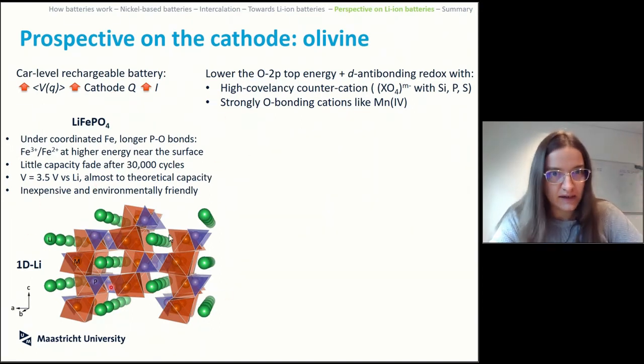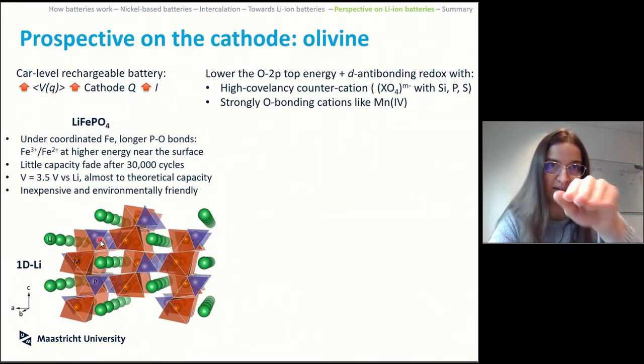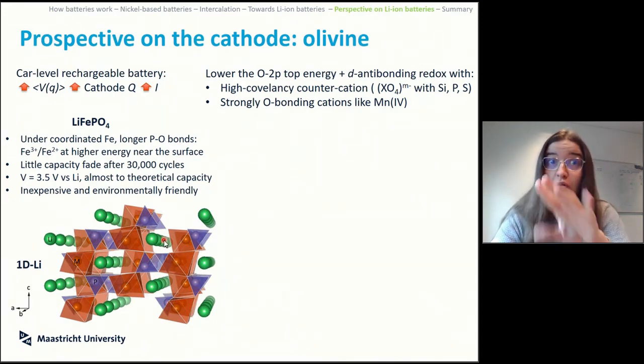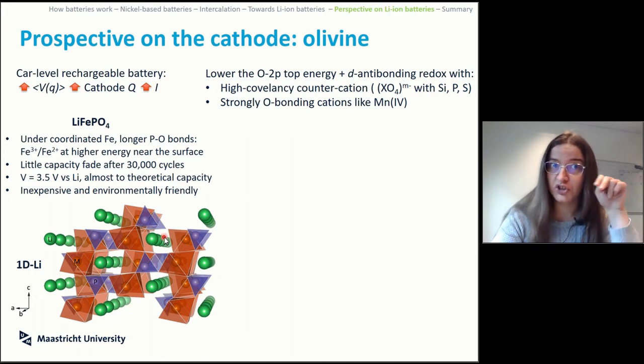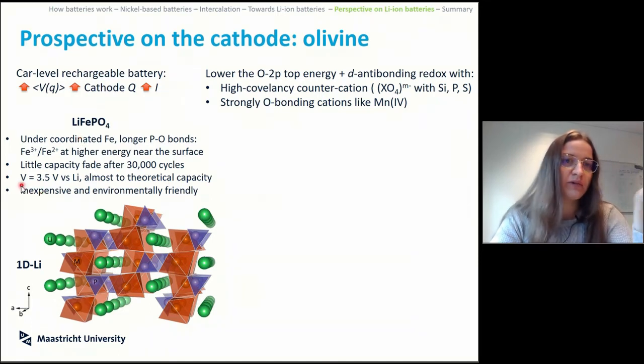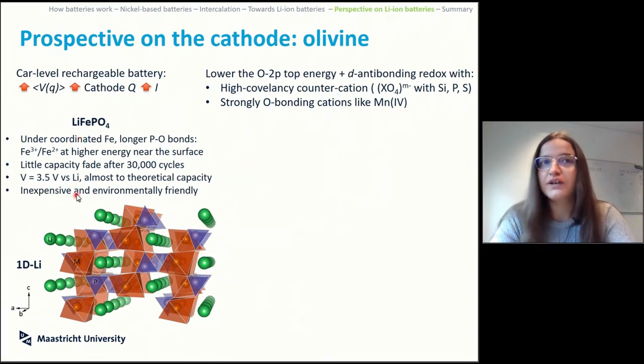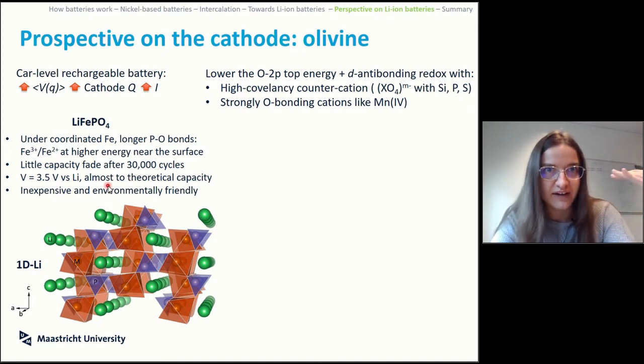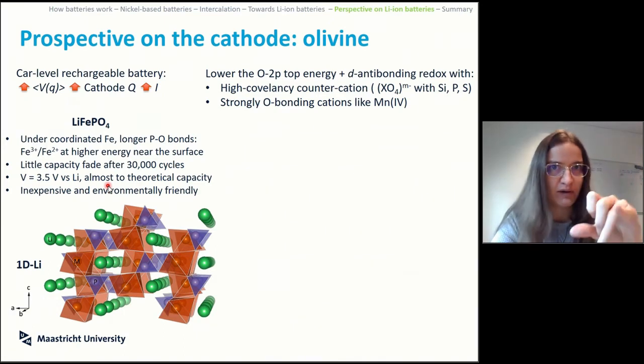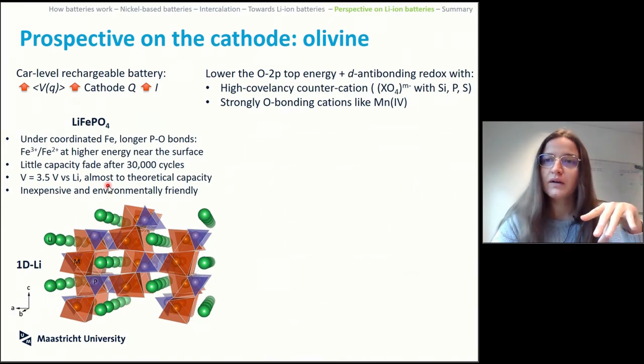This is another battery that can really cycle nicely. And here you need to remember that the lithium is in 1D, because it cannot go through a whole plane, it can only go through a single channel in and out of the structure. These materials are super nice, iron phosphate, everyone likes them, you can find them everywhere. And it will go at 3.5 volt versus lithium, which is a perfectly operable voltage of a battery, almost at theoretical capacity. So the open voltage and the one that you actually get is real.